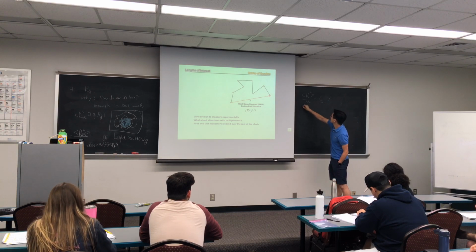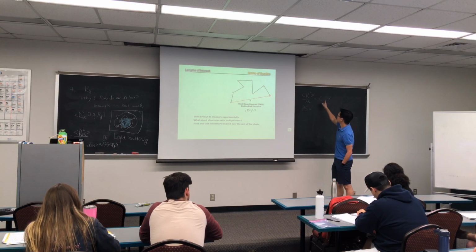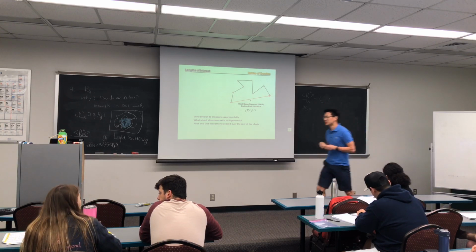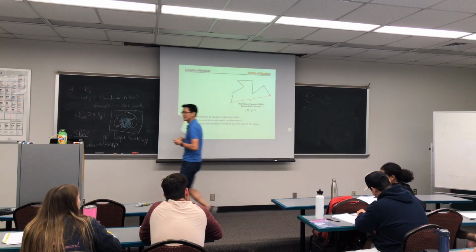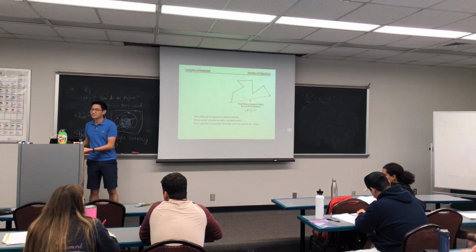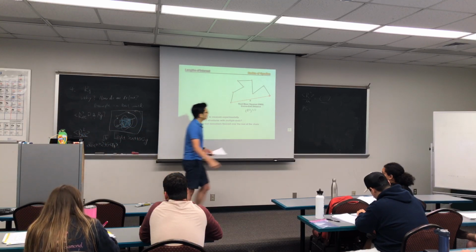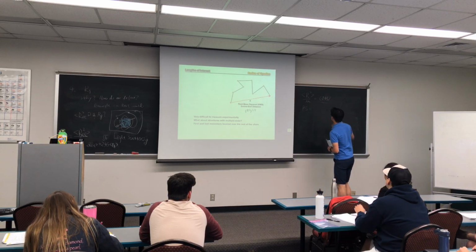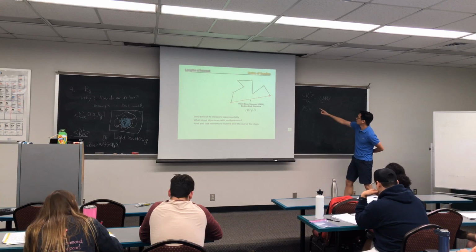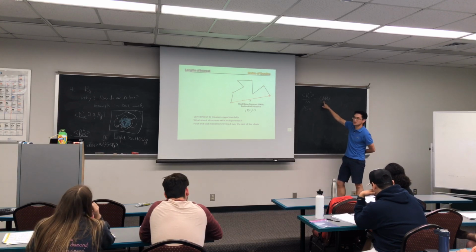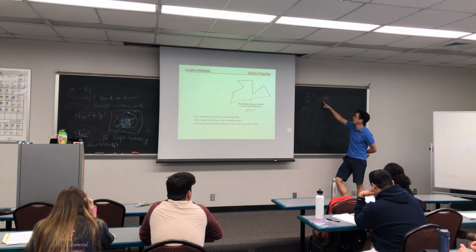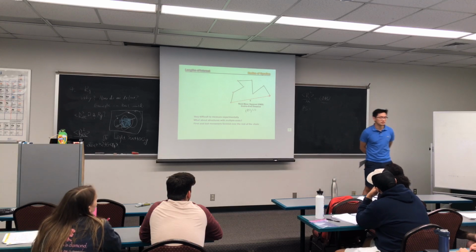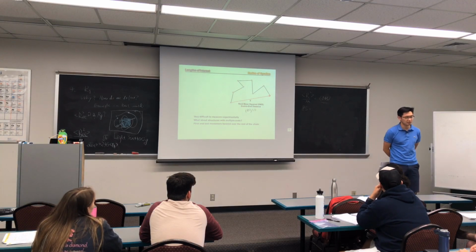If you look at the polystyrene, can anybody tell me what the value is there? I didn't bring my textbook. 0.43. Okay, so if you know the molecular weight is 1 million, you can use this constant, multiply by 1 million, and take the square root. You can get the end-to-end distance. That will tell you how big your polymer is, okay?